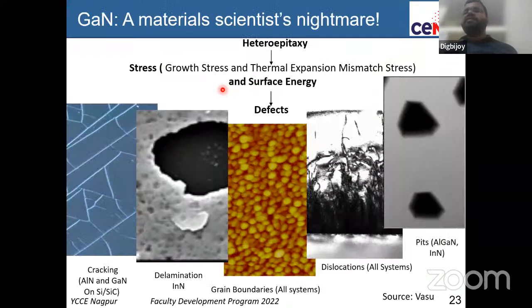So this slide is from Professor Vasu, who is our department chair. I collaborate with him. If you do not grow gallium nitride properly on silicon or any other substrate, it can lead to delamination like this, cracks in the film, very large grain boundaries and uneven surfaces, a huge density of dislocations, which are missing lines, or deep pits that will form.